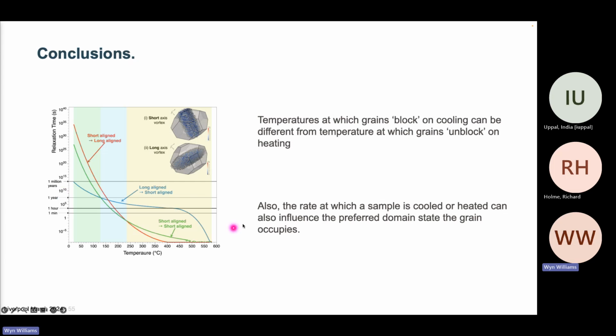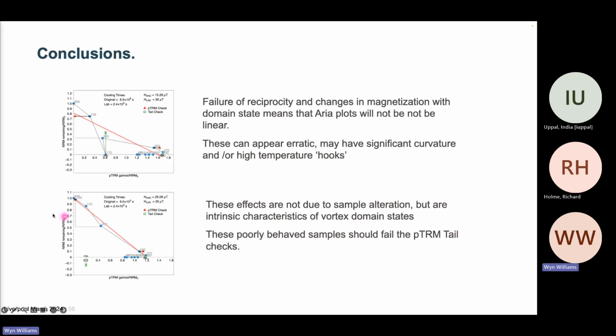Part of the problem is cooling rates, exacerbated by the fact that cooling rates select different populations of grains, which then have different magnetic strengths. It's all to do with this failure of reciprocity. So your erratic plots in your samples may not always be attributed to chemical alteration. If they're not due to chemical alteration, there's a possibility of extracting some data from these, I think, but we're not there yet.